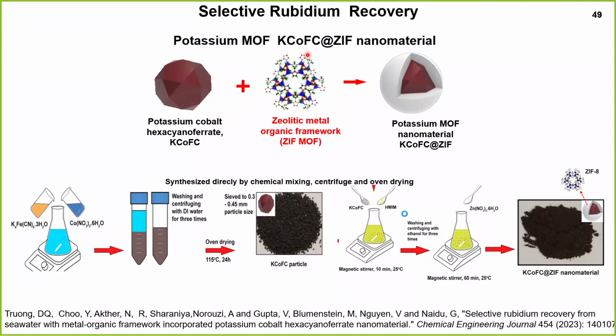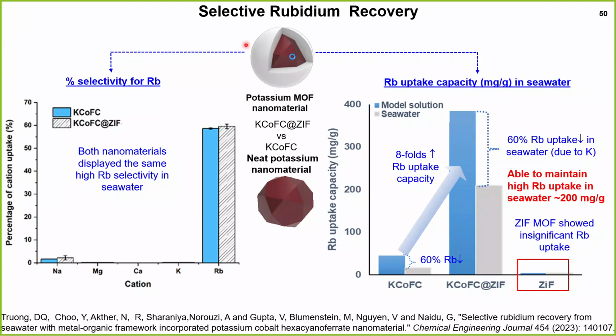So we combined them together and let them adsorb on the surface of this KCoFC, and then we tested this compound. We compared KCoFC and KCoFC with ZIF. For the rubidium compound, they are both relatively good. And then for rubidium uptake capacity in seawater, KCoFC surrounded with ZIF shows almost 8 times higher rubidium uptake compared with KCoFC only.